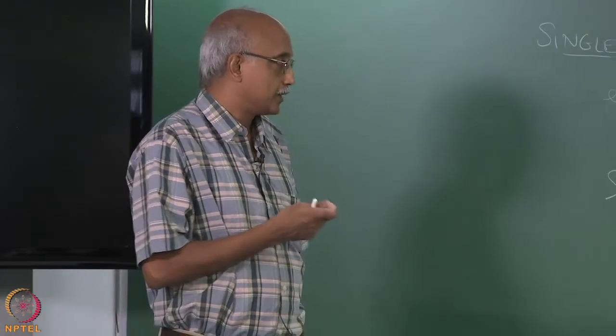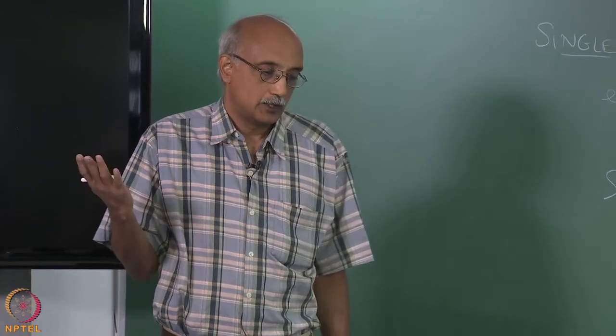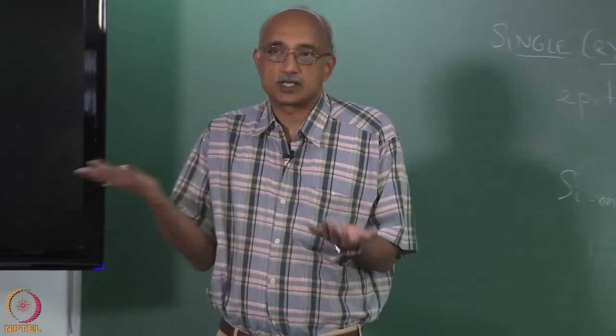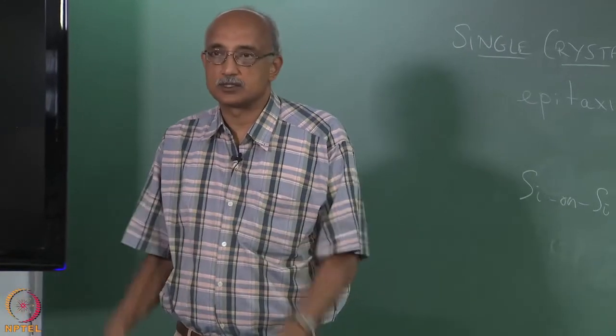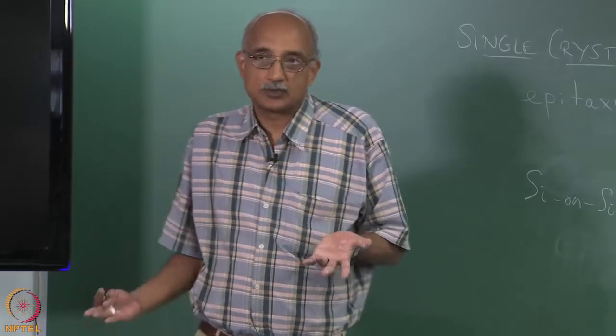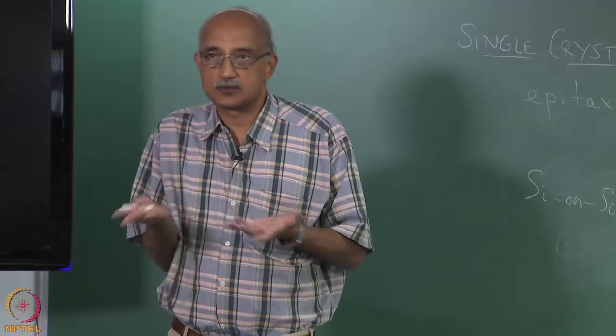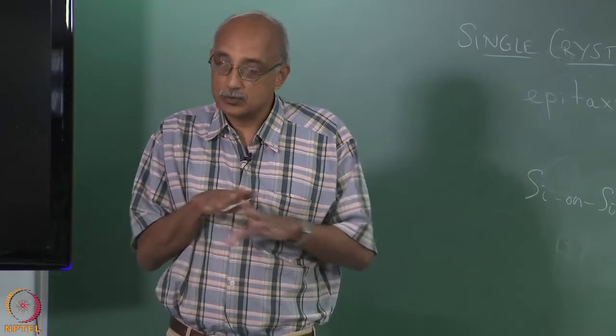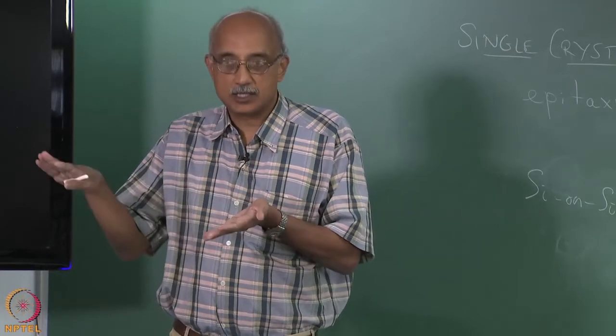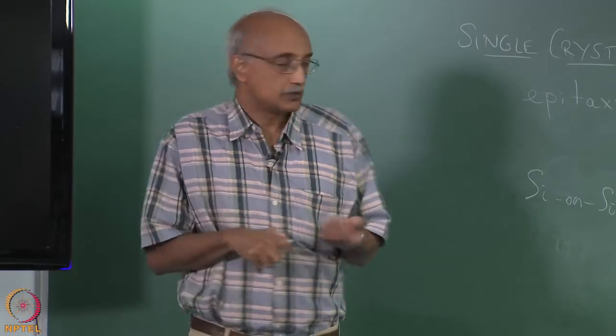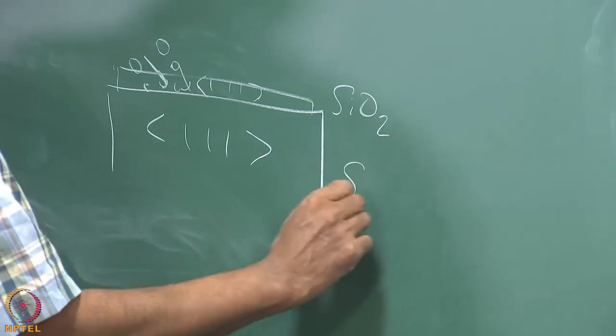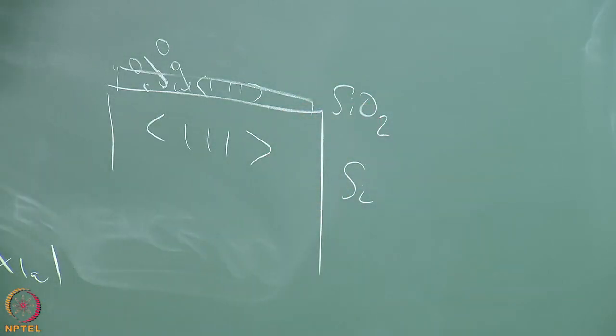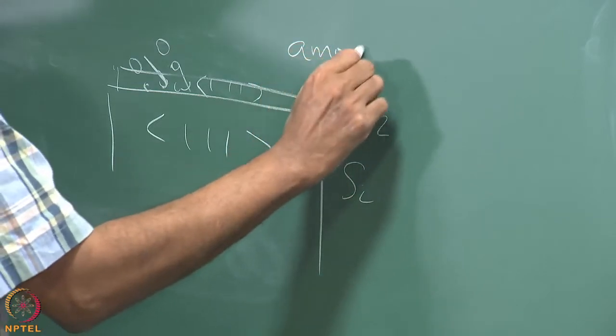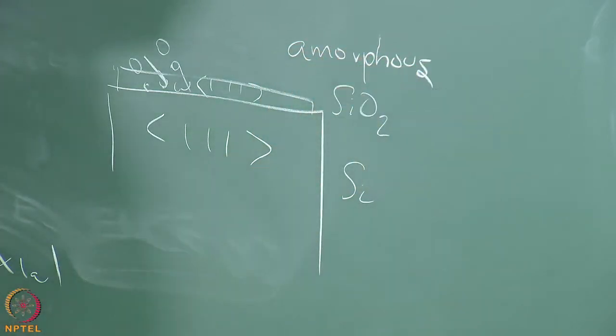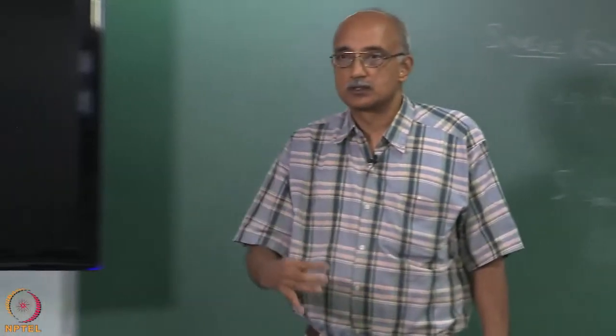But what happens if the silicon itself is not pure silicon, but it has been oxidized? So, you have a very thin oxide film on the surface. Then the arriving molecules are not going to see a crystalline silicon structure to attach themselves to, right? So, instead they will now be trying to replicate the silicon oxide structure that they see on the surface. So, if there is oxygen contamination on the surface which leads to the formation of SiO2 on top of the silicon layer, then the film that results is going to be amorphous in nature, because it matches the surface that it is seeing.